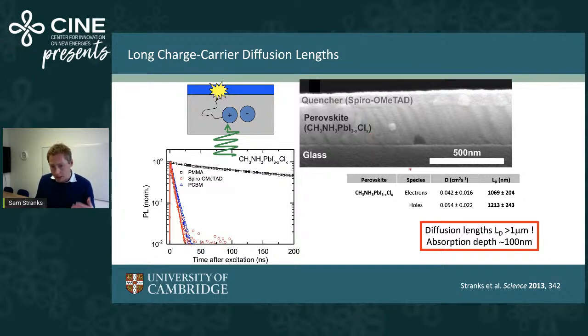And what we can extract from that is the diffusion length. So this is how far these charges can travel before they recombine and lose their energy to heat. And so we found that these diffusion lengths are something like a micron in length. And this is actually a very surprising result, particularly at the time, because what it says is that if we excite in this sort of first 100 nanometers of this film, then these charges can easily traverse that across the absorber layer to a charge collecting electrode and be collected.